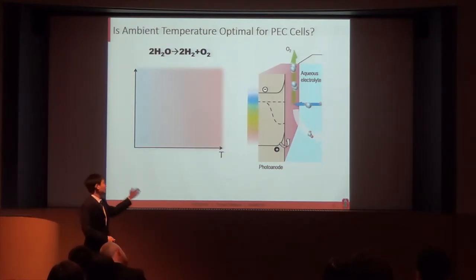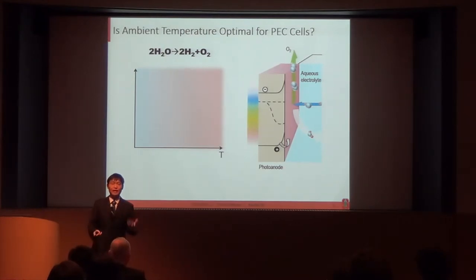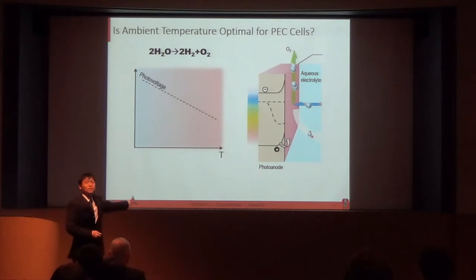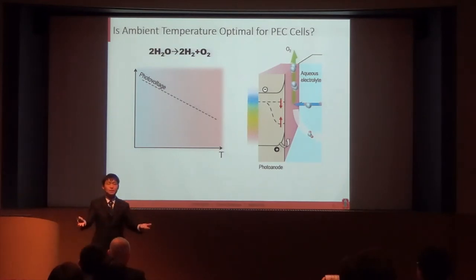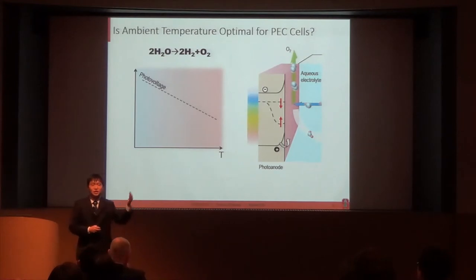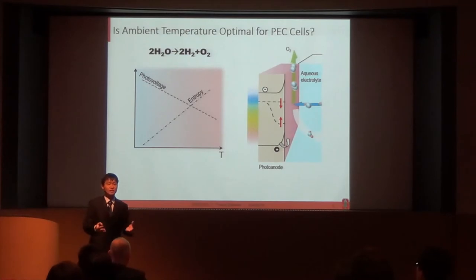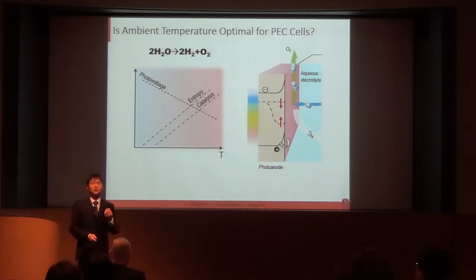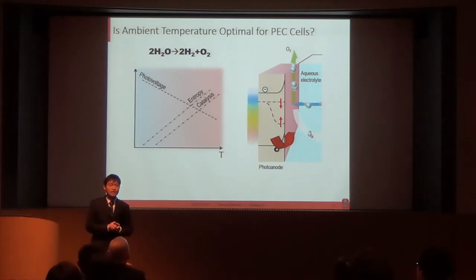To answer this question, I made a list of temperature effects that could apply to PEC cells. First of all, the photovoltage decreases with increasing temperature. This is well known in solar cells. As you increase the temperature, the intrinsic carrier concentration increases, so the quasi-Fermi level splitting decreases. And thermodynamically, the entropy of the water splitting reaction actually goes up with temperature, which causes a decrease in the free energy cost. So that is a beneficial effect. Kinetically, it is also straightforward to understand that catalysis improves with temperature because the reaction becomes faster at elevated temperatures.